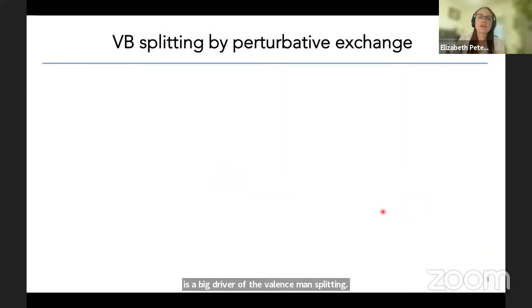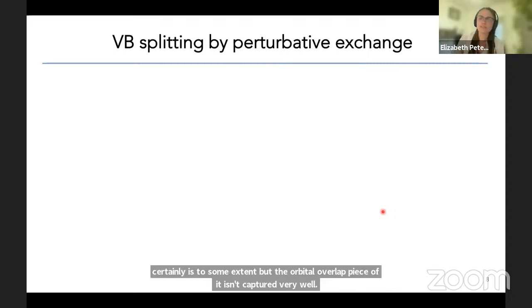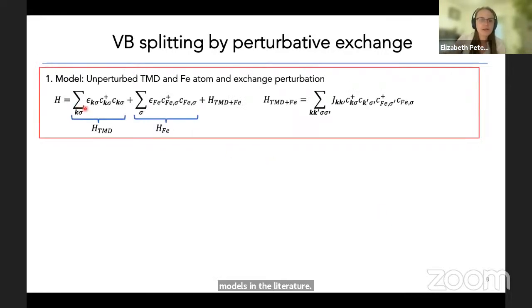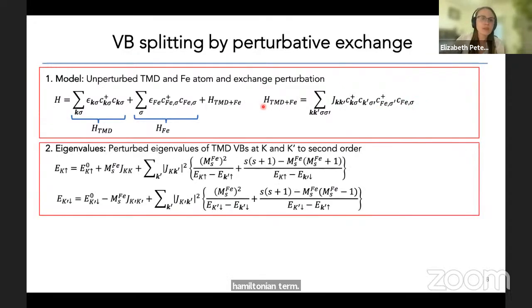And so I wanted to develop a model that could describe this phenomenon. In the literature, typically this is described as a Zeeman-like phenomenon, which it certainly is to some extent, but the orbital overlap piece of it isn't captured very well by existing models in the literature. So what I've done is I've started with a model Hamiltonian where I have the unperturbed transition metal dichalcogenide dispersion, I have the unperturbed iron atom, and I introduced the mixing term. And there's a whole cornucopia of terms that you could develop here. But I pick one that's not going to be necessarily the same at K and K prime, a sort of effective exchange model Hamiltonian term. And I treat this as a perturbation. And when I do that, I can go to second order in the eigenvalues and look at how they're affected by this perturbation. And what I find is to first order, I get a quantity that's sort of equal and opposite, where this capital M_S^Fe is the spin magnetic quantum number of the iron atom.